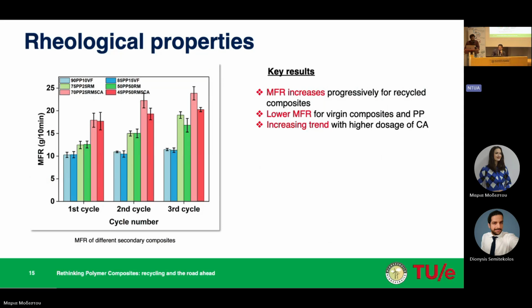yeah, we are not developing such materials just for lab scale, right? We also need to have these materials which can be upscaled on an industrial level. So for such a thing to happen, we also need to have good rheological properties for these materials. So as you can see here, the melt flow rate of these composites was progressively increasing over the number of cycles. The recycled composites had better melt flow rate compared to the virgin ones. The main reason for such a thing to happen is that